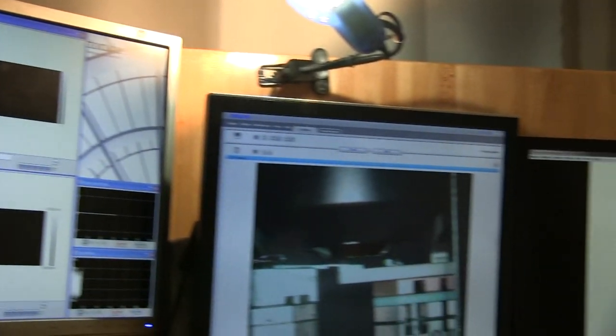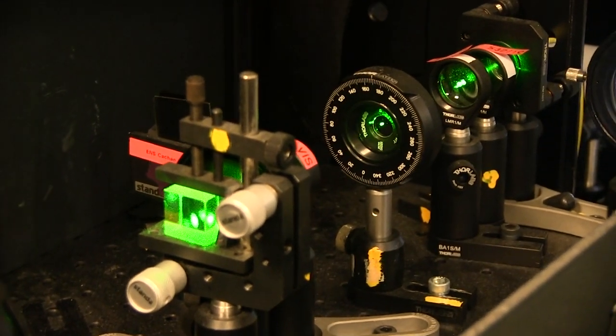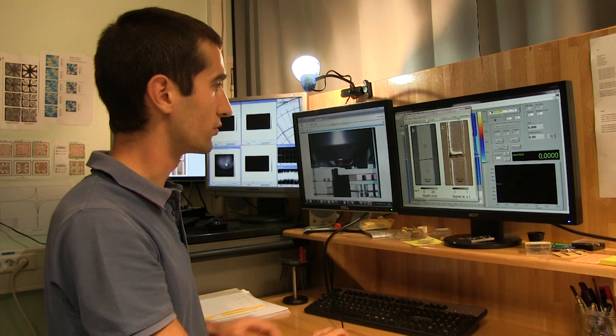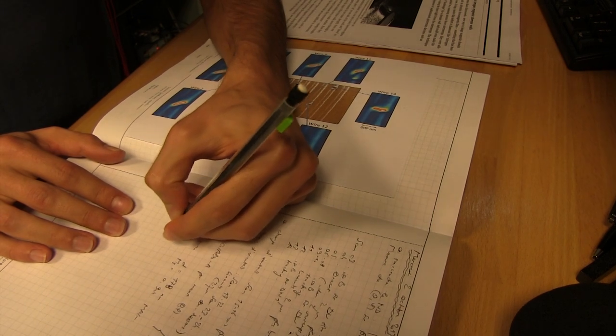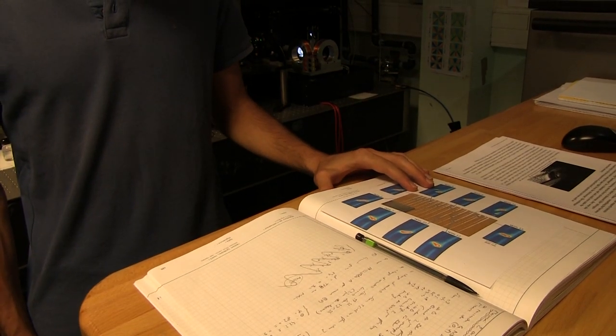Being able to move nanometric walls may sound a bit esoteric, but this microscope could actually help industrial research. There's an IBM project called Racetrack Memory that will let you read and erase information with spintronic devices. But for this you would need to know your domain walls very intimately. And this is what we are able to do now with this microscope. We are able to characterize the stable position of the domain wall and this is what you want to be able to engineer and improve the materials that we use for this racetrack memory.